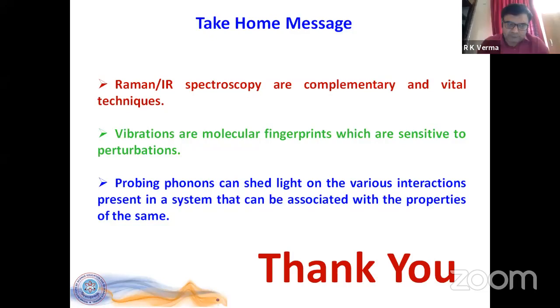But the some amount of energy is given to the sample which creates the phonon. On the other hand, in the anti-Stokes case, the laser can take some energy from the sample, by annihilating or killing some of the phonons. And that's when the energy of the light will be higher than the incident light. And that is the anti-Stokes. Overall, you see the energy is conserved, but there is a give and take process in the energy to the system from the laser light.